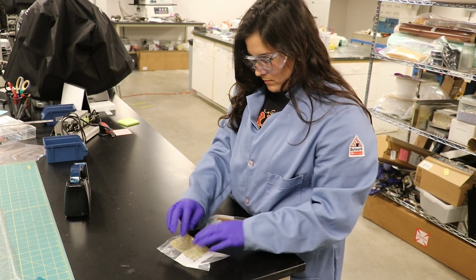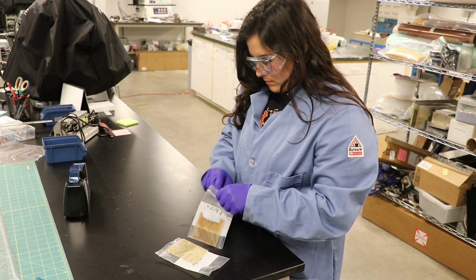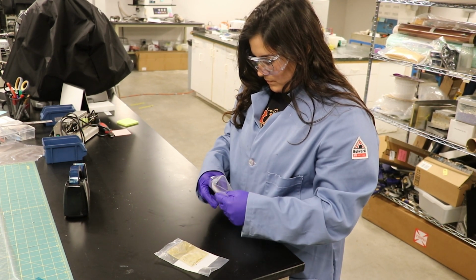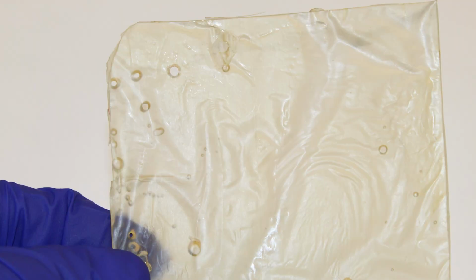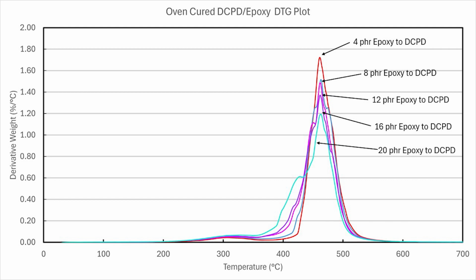We first looked at phase separation or resin compatibility as measured by cloudiness after cure, since the two polymers are both clear when they're cured alone. We observed that the samples within that 12 to 20 parts per 100 epoxy range are clear after curing and thus compatible at the macro scale. We next looked at thermal stability of the cured resin as measured by weight loss as a function of temperature, in which the 12 through 20 parts per 100 epoxy formulation range are shown to be thermally stable up until around 300 degrees Celsius, which is much higher than the temperatures expected during processing or service in space, and suggests the two polymers are highly cross-linked.